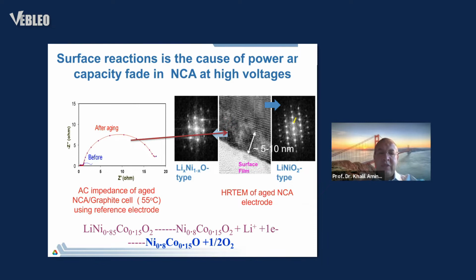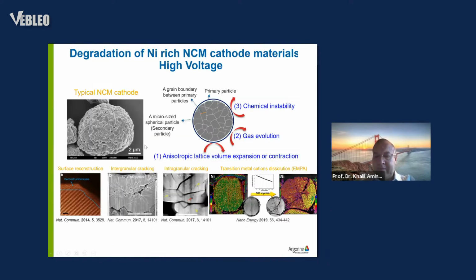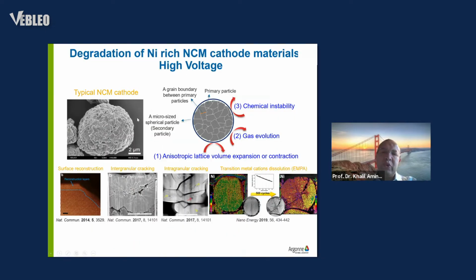Now, what the industry has been doing so far is to do coating to prevent this type of reaction. So this is the typical coating that the industry is using. So basically, this is what happens. When you do a coating, you basically disperse nanoparticulates of metal oxide or metal fluoride on the surface of the material, to form not exactly a film, but just a nanoparticulate deposit on the surface. So you don't cover the whole surface, but those can actually impact the stability.